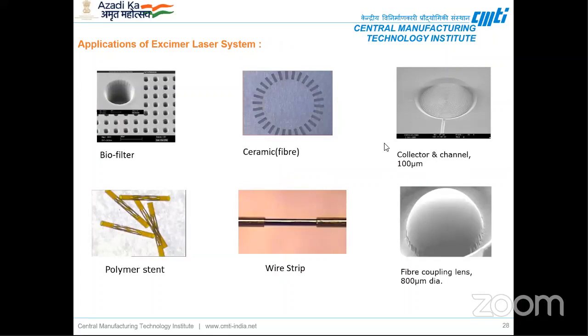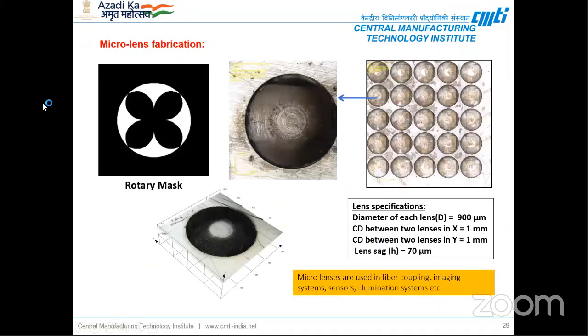Some of the applications of the excimer laser system are in biofilters, ceramics, collector channels of around 100 micrometer feature size, micro lenses, that is fiber coupling lenses, wire stripping, and we can even fabricate polymer stents. The work we have carried out at CMTI using the excimer laser is a micro lens array of 5 by 5 size. The diameter of the lens is around 900 micron, with a center distance of 1 mm in x as well as y direction, and a lens sag of around 70 micrometer. This kind of lens is used in fiber coupling, imaging systems, sensors, illumination systems, etc.